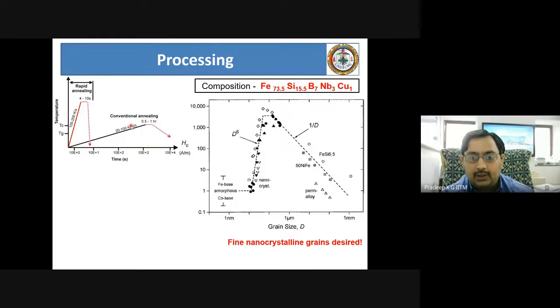And there are different industrial methods available to produce these alloys with fine nanoscale grains. The conventional one is heating it at a certain temperature for 1 hour and then cooling it slowly so that you get a fine nanoscale microstructure. The alternative method is you heat it at a very high heating rate, put it at a certain temperature for a shorter time, but that temperature is much higher than that of conventional annealing.